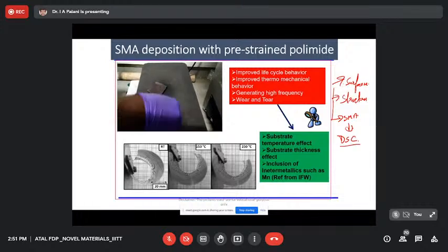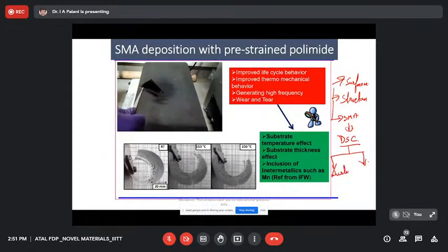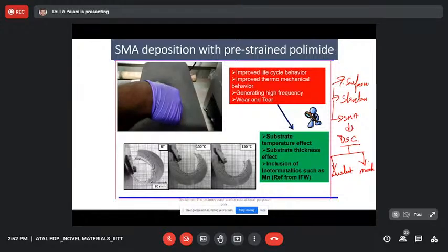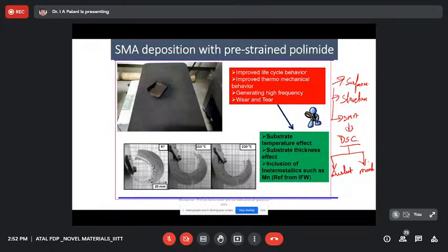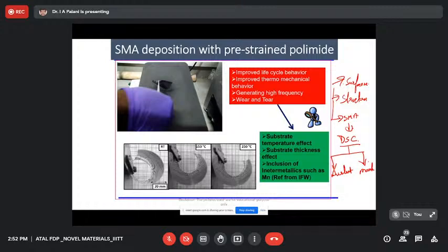The main functionality of this DSC is that it will give us clarity about the austenite phase and the martensite phase of the material. It has a phase transformation behavior, so we can study the phase transformation both in a hot condition as well as in a cold condition. In a hot condition, we can supply a temperature to it, and in the case of a cold condition, we can go to a low temperature, up to -180. So we have the capability to go from -180 to 650 degrees Celsius to study the transformation characteristics using DSC.